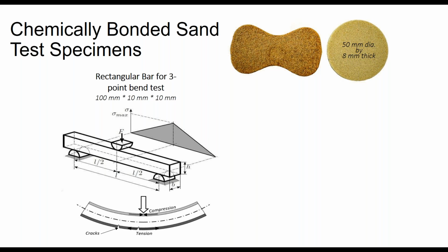We have a cookie shape that is now a standard, the traditional dog bone, and I'll keep things in simple shapes here, the Kit Kat bar, the rectangular beam. Well, certainly most people know the dog bone for chemically bonded sand testing. The shortcoming with this specimen is that it does not always break where it's supposed to, right at the slender part of the specimen. It breaks across the shoulder to the hip, or across the hip or the shoulder, affording specimen to specimen variability in a mechanical test.